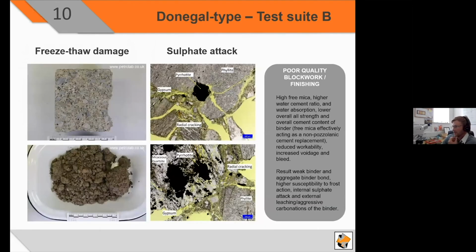If we move over to look at County Donegal type or free mica type, deterioration is largely driven by freeze-thaw action. We have an example here of an internal freeze-thaw test where samples were cycled through freezing and heating cycles, breaking down the aggregate cement bond and leading to sample deterioration in approximately 30 cycles. The freeze-thaw damage is activated by the distribution of free mica throughout the binder. It's quite highly water absorbent and will take up the water and then release it during the freeze-thaw cycles, working to expand the aggregate against the binder, forcing the freeze-thaw damage.